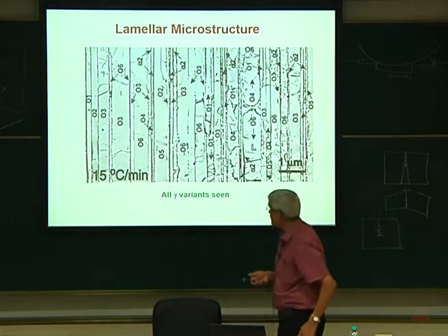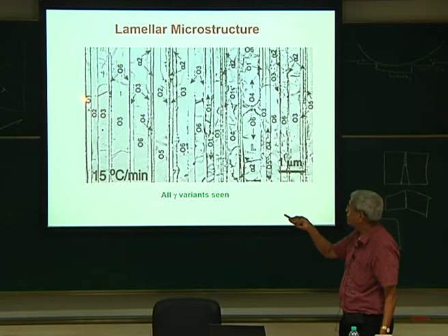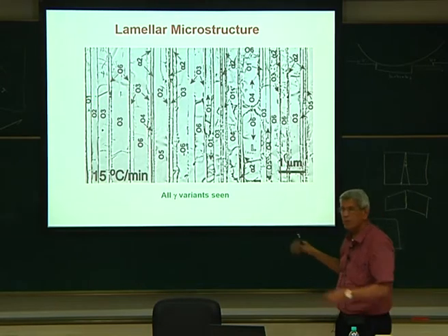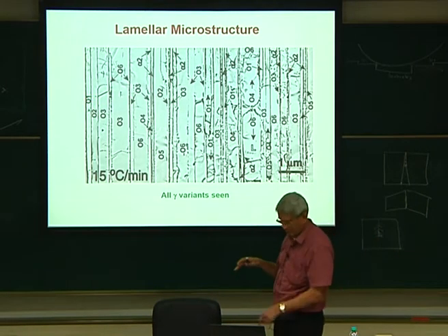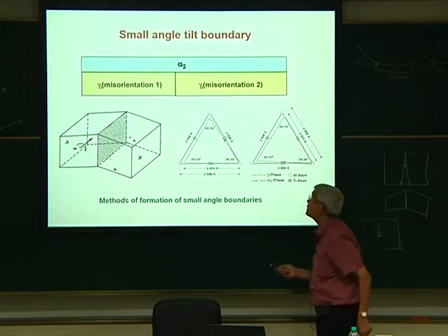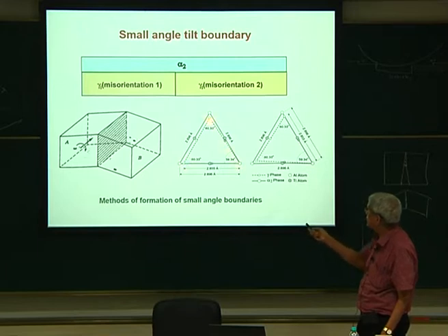Essentially, what is shown here is all the variants which will form, which have been imaged in an electron microscope and then indexed. This is what is being written, O1, O2, some order number has been given depending upon that orientation. But what is essentially important is that I call one as an orientation. What is shown here is the close packed plane of the HCP lattice, and the ordered lattice is being shown because it is a right tetragonal distortion.